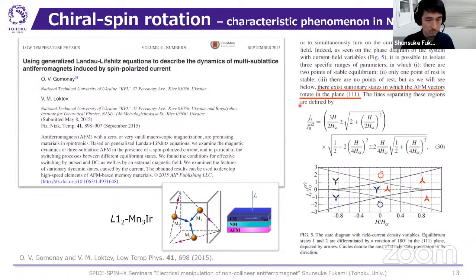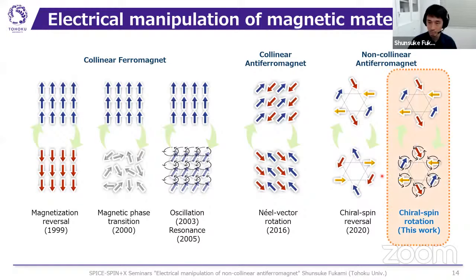According to this paper, she mentioned that there exists a stationary state in which the antiferromagnetic vector rotates in the 111 plane. She derived this phase diagram, and in certain areas, the chiral spin structure rotates in the clockwise or anti-clockwise direction at zero magnetic field. So this is clearly different from ferromagnetic oscillations, because the rotation can be induced at zero magnetic field. Today I will show that the chiral spin rotation can be observed in the non-collinear antiferromagnet as Gomonay predicted.